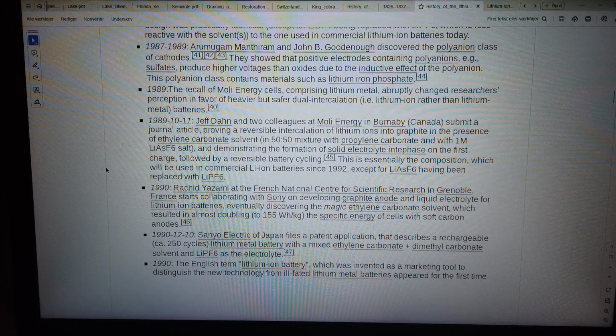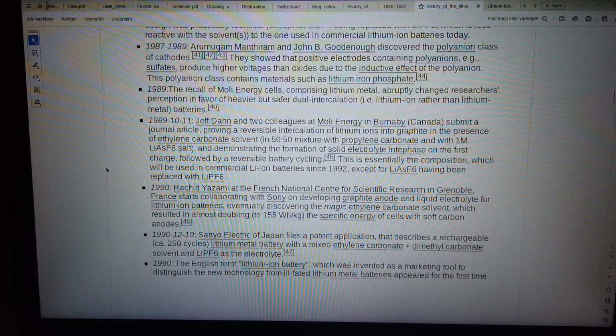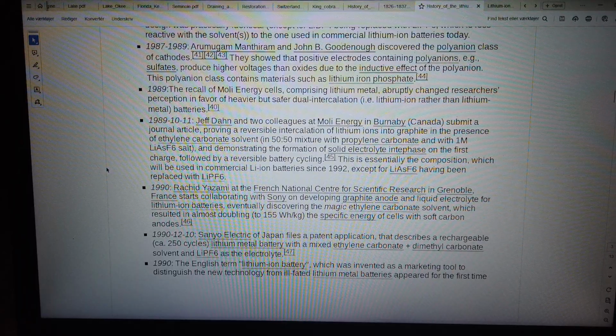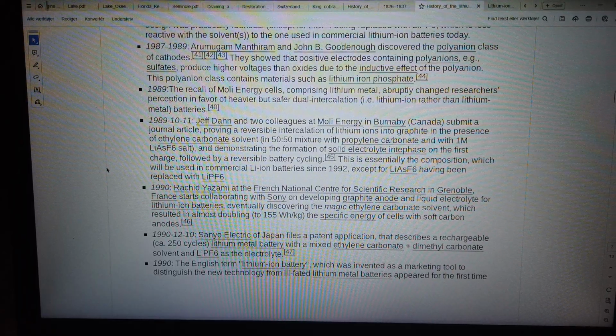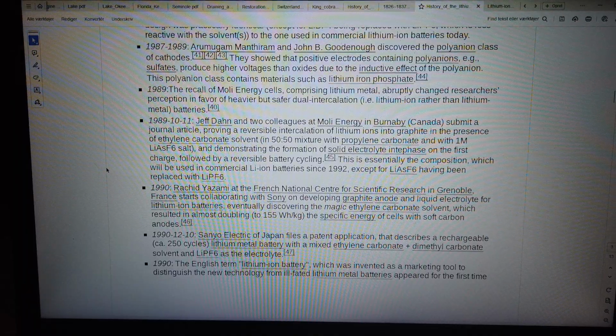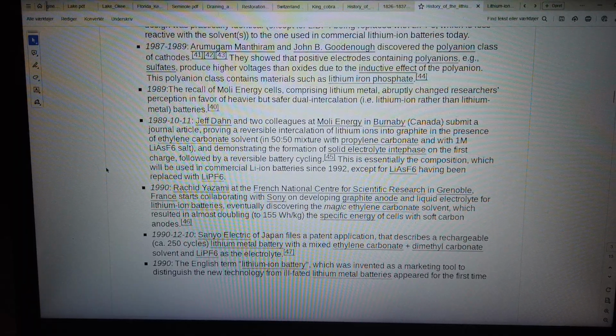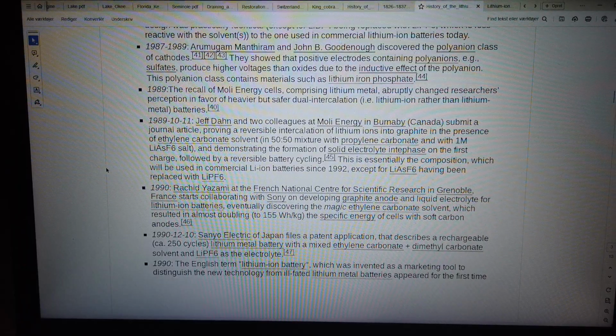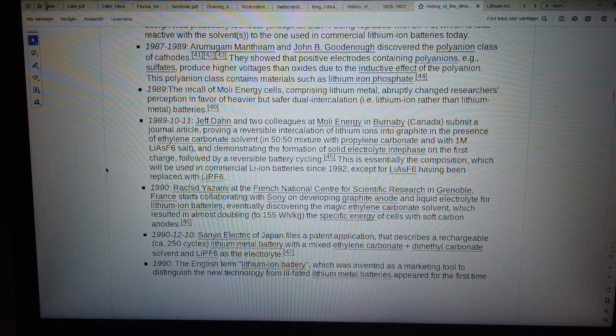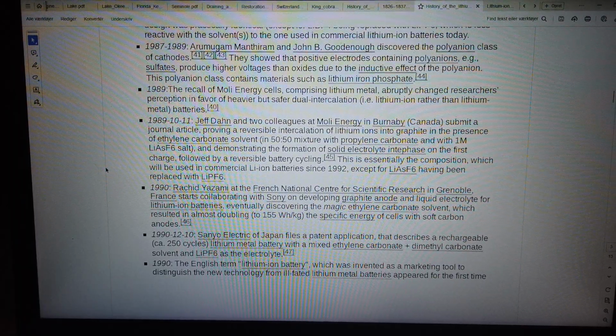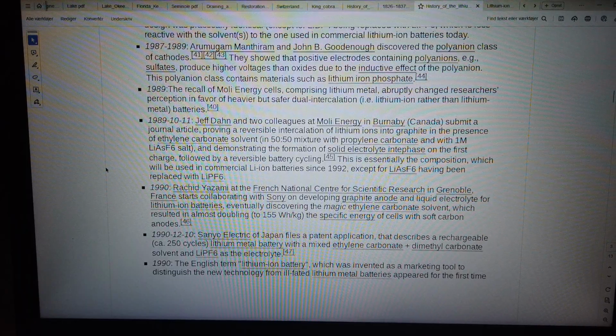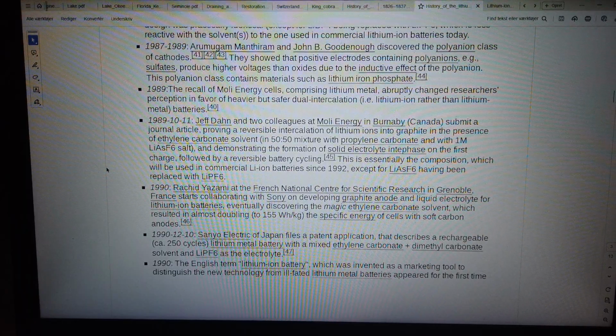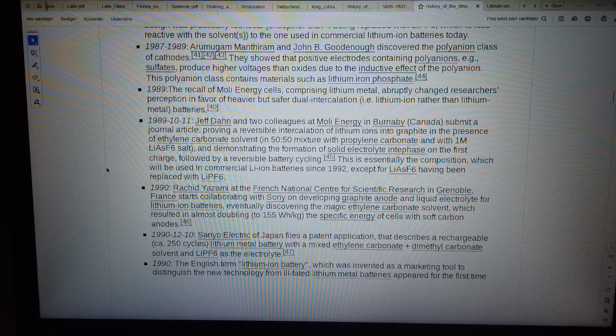Liquid electrolyte for lithium-ion batteries, eventually discovering the magic ethylene carbonate solvent, which resulted in almost doubling to 155 Wh/kg the specific energy of cells with soft carbon anodes. 46. The 10th of December, 1990, Sanyo Electric of Japan files a patent application that describes a rechargeable, ca. 250 cycles, lithium metal battery with a mixed ethylene carbonate and dimethyl carbonate solvent and LiPF6 as the electrolyte.